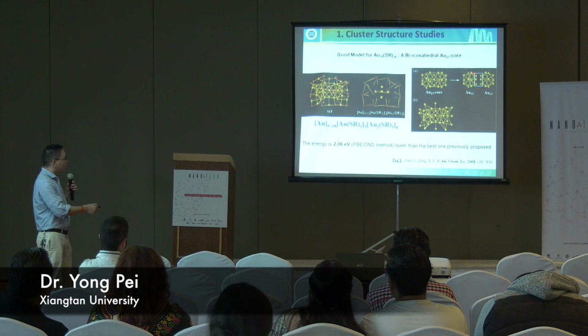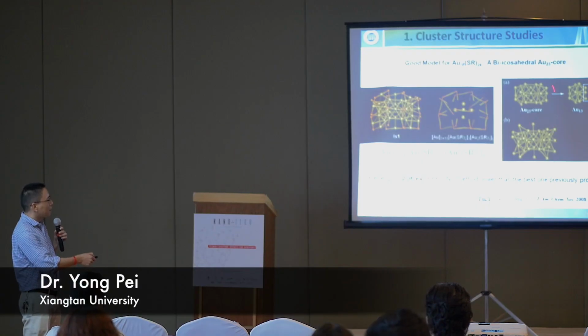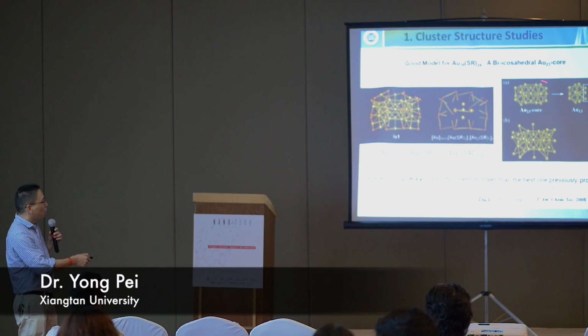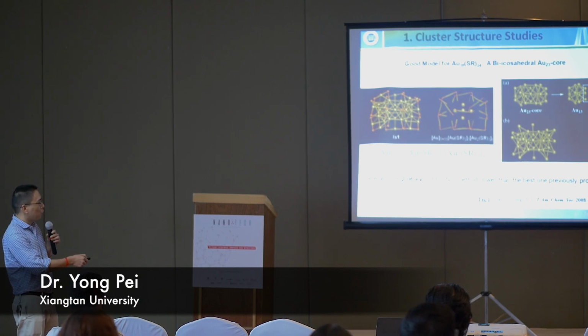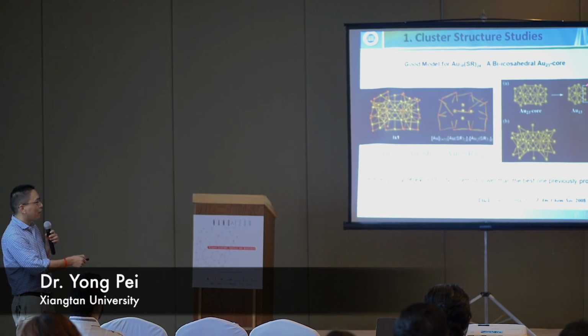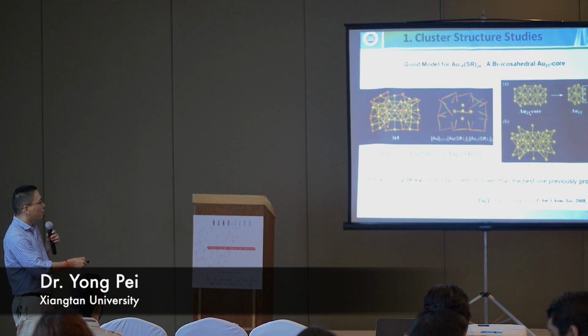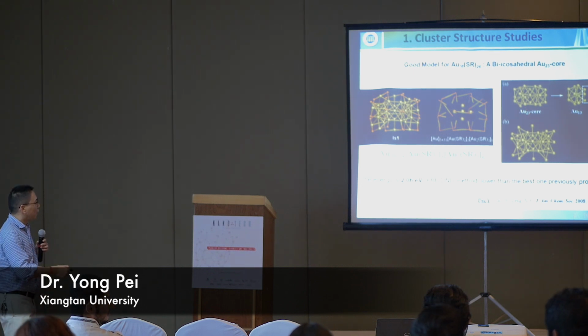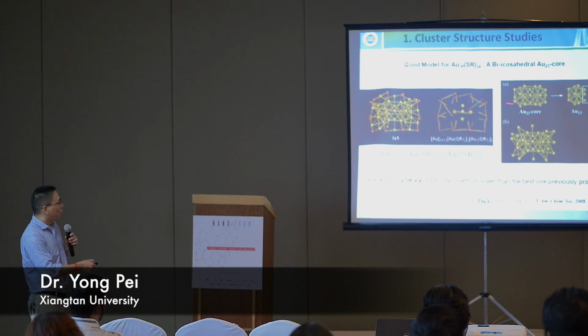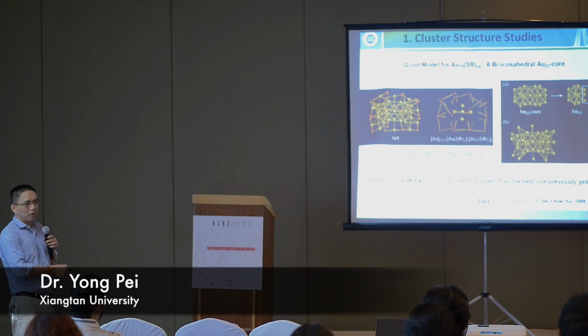Finally, we obtained this core. This gold core is made of two icosahedra, and the two icosahedra share a triangle face. The total number of gold atoms in this gold core is 23. We found that this structure model is very stable because it has very low electron energy.